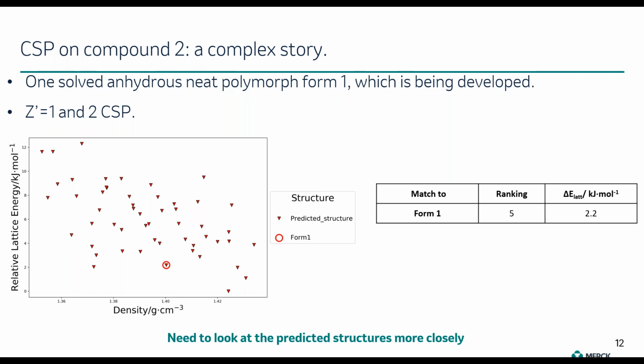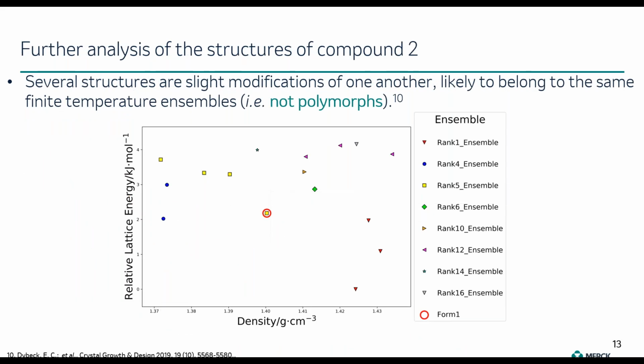So we decided that the best approach was to look at some of the predicted structures more closely. And what we realized is that several of them are not very dissimilar to one another, but have slight modifications, which we assessed are likely to belong to the same finite temperature ensembles. So basically, they would not be able to crystallize separately at finite temperature, but vibration would likely average them out, and they would belong to the same.